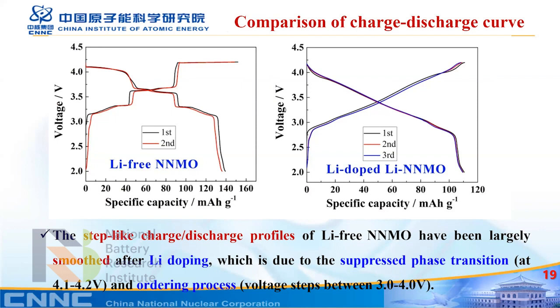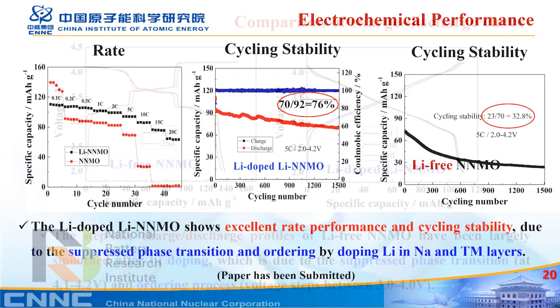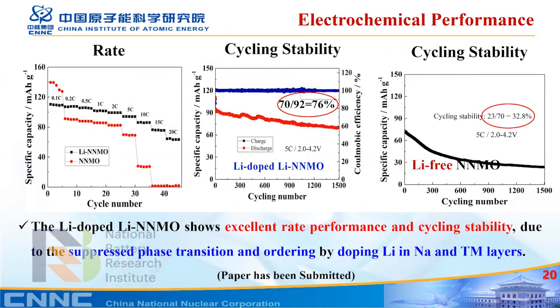Let's see this slide. As shown in the left picture, the lithium-doped material shows excellent rate capacity, improved a lot compared with the non-doped materials. This material can be charged and discharged at very high current density, up to 20 C. As shown in the right two pictures, the lithium-doped material also shows excellent cycling stability after 1500 charge and discharge tests. It still has 76% of its original capacity, but for the non-doped material, only 33% of the original capacity remains under the same condition. We believe the excellent performance of the lithium-doped material is due to the suppressed phase transition and ordering process. That is my introduction about the first part.